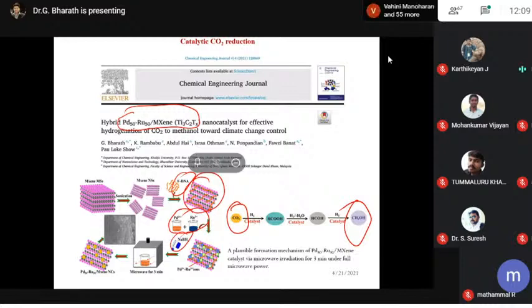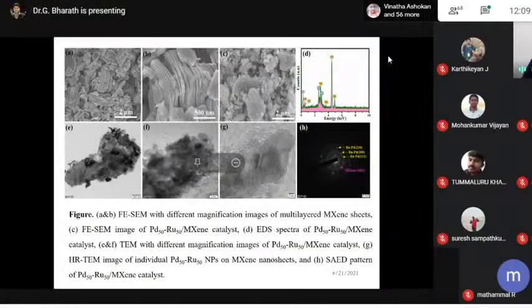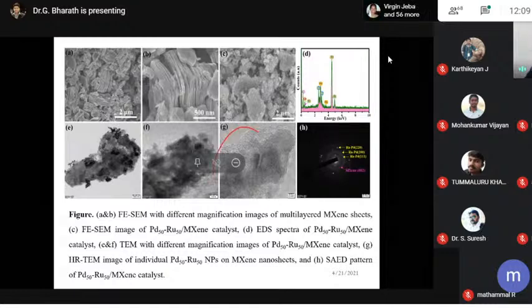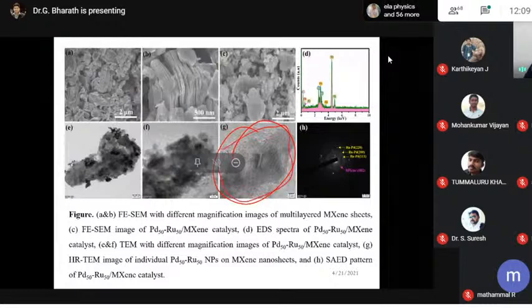We used this for converting palladium ions to palladium nanoparticles. So these are the plausible mechanisms. And then this one shows the FESEM and TEM morphologies. If you look, this is the complete one. This is the MXene sheet, and our nanoparticles are deposited here. This is completely palladium-ruthenium nanoparticles.